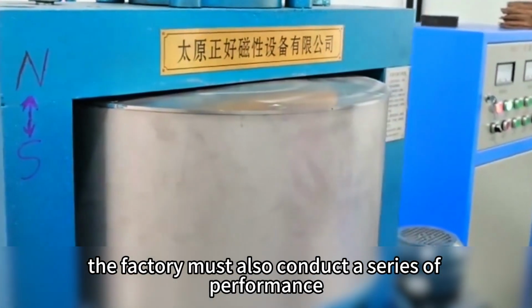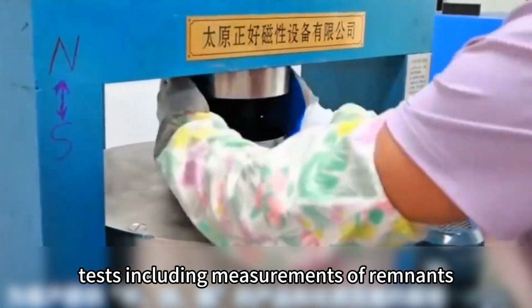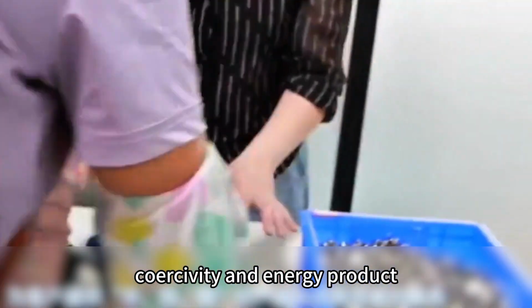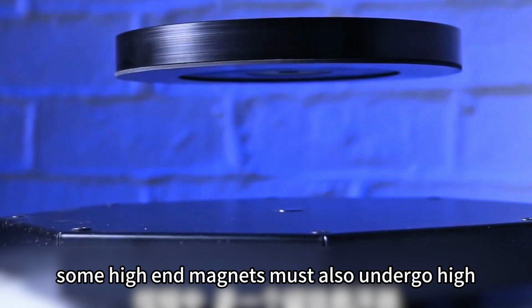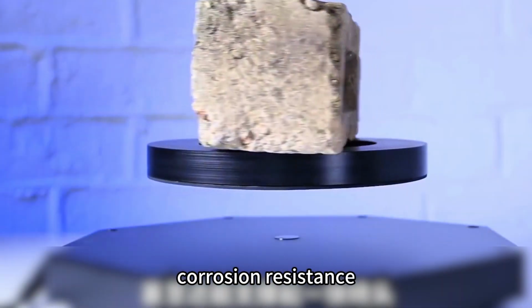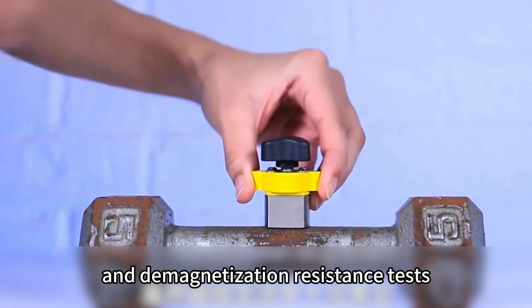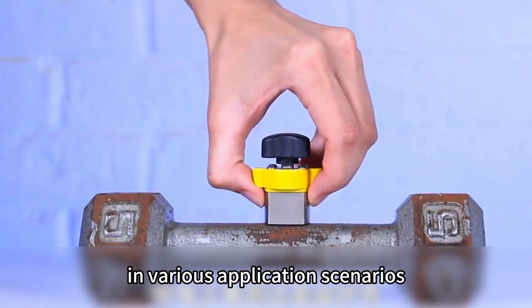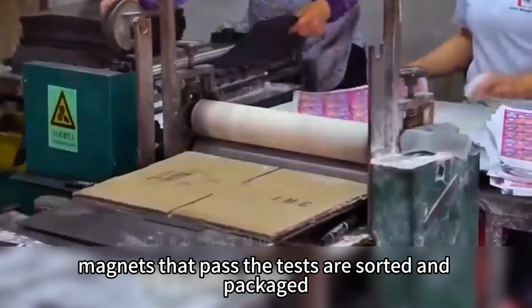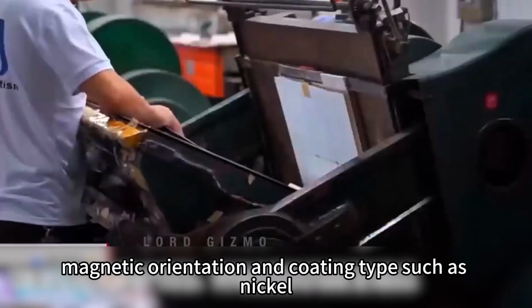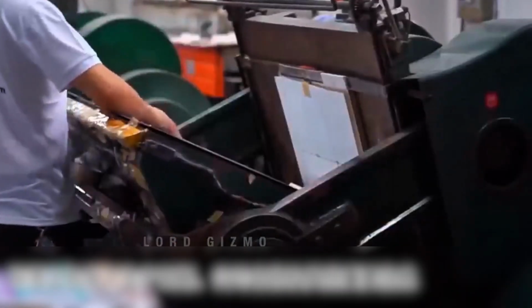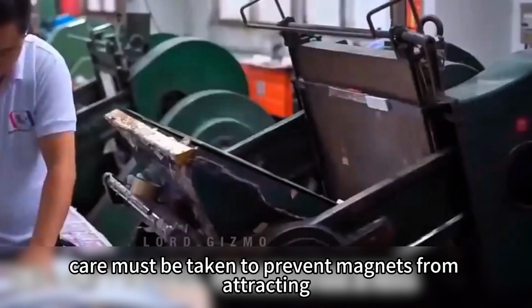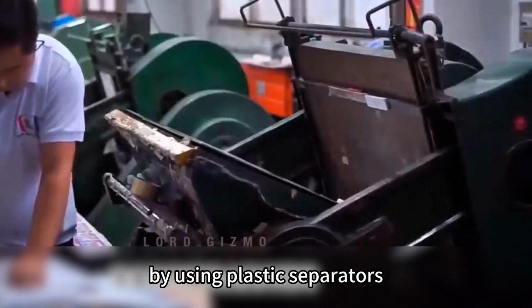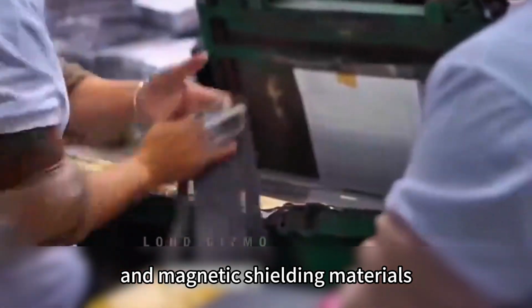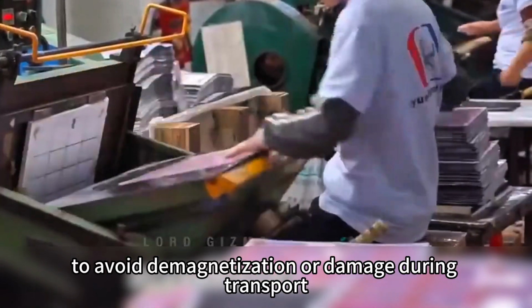The factory must also conduct a series of performance tests, including measurements of remanence, coercivity, and energy product. Some high-end magnets must also undergo high-low temperature cycling, corrosion resistance, and demagnetization resistance tests to ensure stable performance in various application scenarios. Magnets that pass the tests are sorted and packaged according to size, magnetic orientation, and coating type, such as nickel, zinc, or epoxy coatings. During packaging, care must be taken to prevent magnets from attracting and colliding with each other by using plastic separators and magnetic shielding materials to avoid demagnetization or damage during transport.